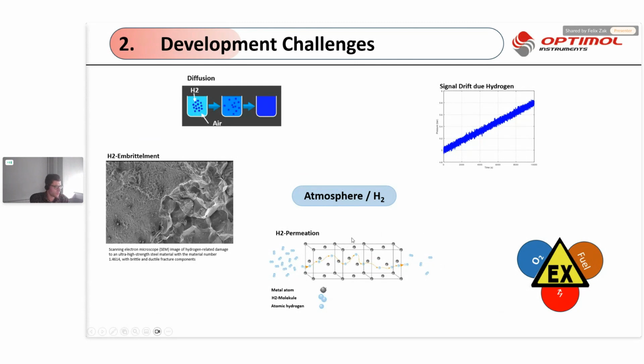on grain boundaries or on pores, or in general imperfections, and there it leads to a blocking of the sliding layers within the materials, and this will lead to an embrittlement, and so the loss of ductility.